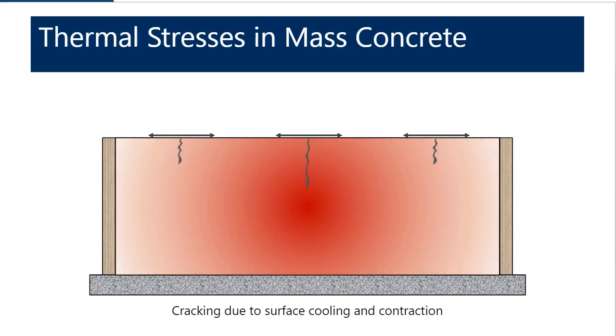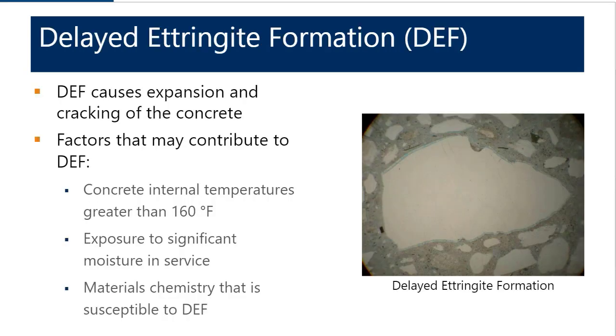One of the other things that we're concerned about is this phenomenon called delayed ettringite formation. And DEF, or delayed ettringite formation, is the formation of ettringite after the concrete has already hardened, which can later cause the expansion and cracking of the concrete. And so under certain circumstances, primarily exposure to elevated temperatures during curing, the ettringite is suppressed and then may form after the concrete is hardened. And so that volume of the ettringite compound is larger than the volume of the original component materials, which can lead to the internal expansion and subsequent cracking of the hardened concrete.